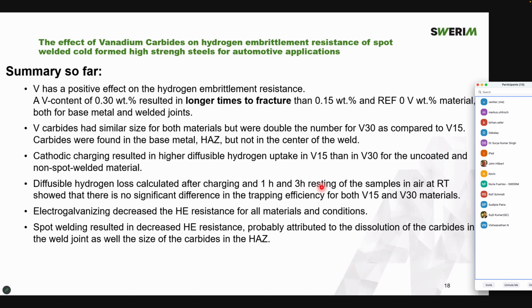And this applies mostly for the heat affected zone, and only for the 0.30%. A few carbides were found in the actual weld.